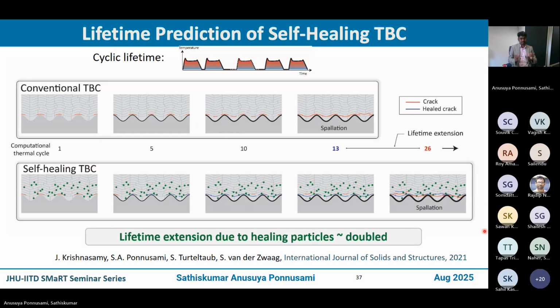But the problem is, even though you know that due to healing the lifetime will extend, you cannot control the ingredients, the design parameters. It's quite difficult to control. So you need to know which design parameters are quite influential in affecting the lifetime, so that the material scientist can design those parameters to optimize the system, right? So what we did here is we did not build a surrogate model for the purpose of predictions. That's really important. Rather, we built a surrogate model for the purpose of quantifying the sensitivity of different design parameters of interest to the material scientist, and we assess those so that you can give useful guidelines to the scientist to develop these systems. Which is quite different from what machine learning models are typically used for.